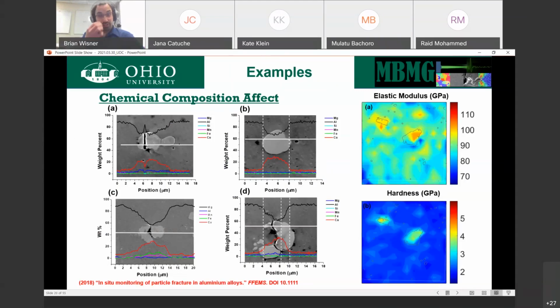But the real takeaway here is if we want to think about this, the material is made of aluminum, and these particles are essentially embedded in it. It's basically like a composite. And if we map the material properties around this area, you will see that there are concentrations of elastic modulus and hardness that are different from the surrounding aluminum. This difference in mechanical properties is going to cause stress and strain concentrations and lead to failure.